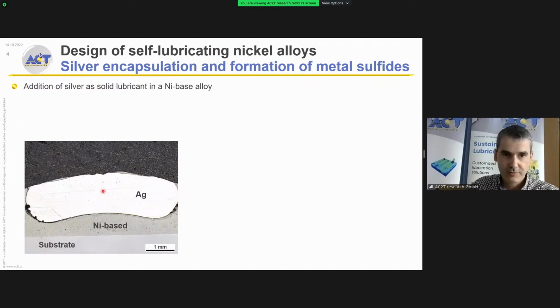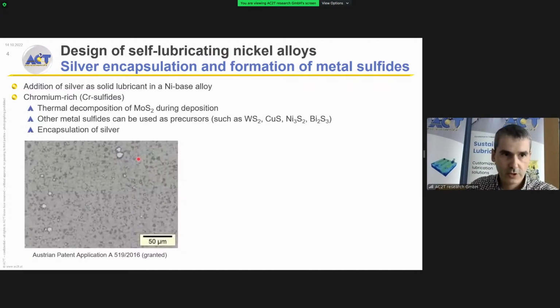So if we want to have something useful, we need to have this solid lubricant homogeneously scattered and distributed in the microstructure. And to do this, we need to have some diffusion barriers for the silver, and we can do it using, for example, sulfide compounds. So in our case, we use molybdenum disulfide that during the thermal deposition decomposes into chromium sulfide. This means that this process is not limited to molybdenum disulfide. Other sulfides can also be used as a precursor, but once we use these sulfur compounds, we end up having this microstructure with the characteristic nickel dendrites, and the silver, like these light gray silver inclusions that are surrounded by these dark gray chromium sulfides.